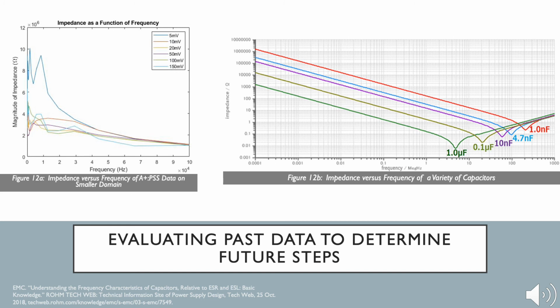The exact circuit model that corresponds to the complex network of parallel and series electrodes in our composite has yet to be carefully analyzed. But we did notice the following trends in this data: that the impedance appears to be independent of applied voltage at high frequencies, which suggests a parallel resistor-capacitor circuit network, and the low frequency impedance is higher at low applied voltages, which may be correlated with the energetic barrier between the materials of our composite. Although we cannot actually conclude anything from this data, these do pose questions that we can test later and then draw conclusions about the electrical properties of PEDOT:PSS for capacitors.